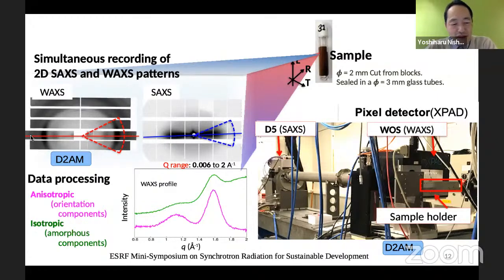And what we see here in the lateral direction corresponds to the lateral packing inside the specimen. From this 2D pattern, you can separate the signals into something that is anisotropic, which is this streak feature, and something that is this broad and isotropic background. So this is an example of separating the intensity into two components, an isotropic and an anisotropic. And then from here, we are just focusing on the anisotropic, which corresponds to the lateral packing inside the cell wall.